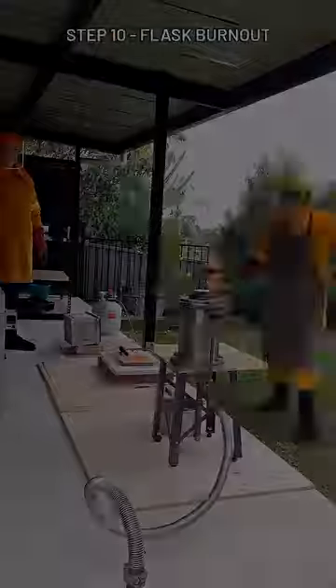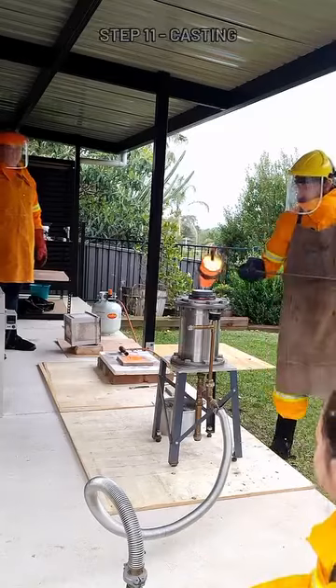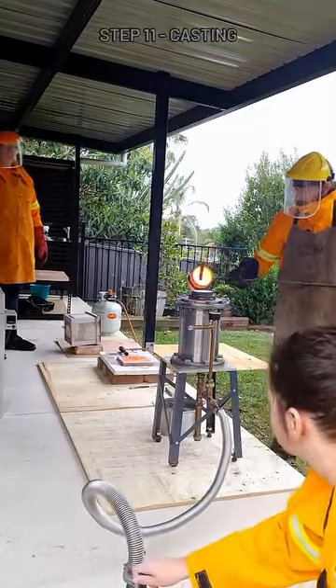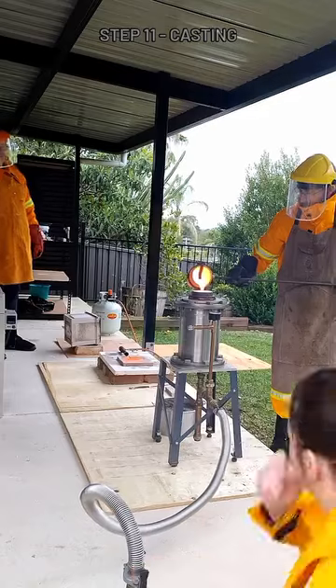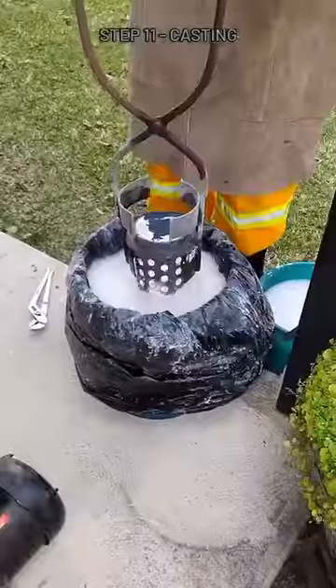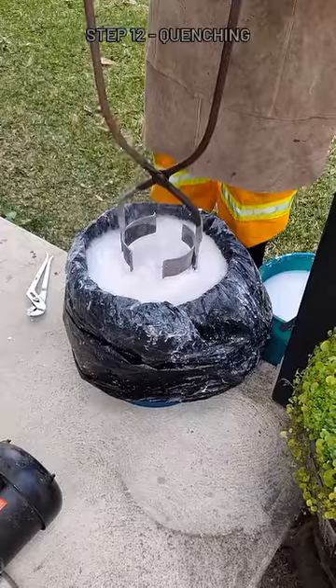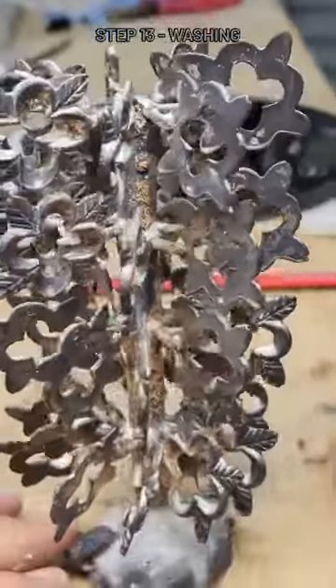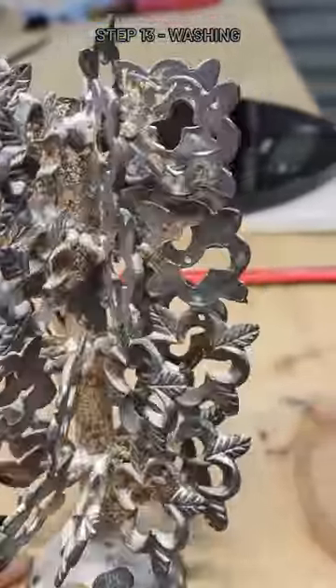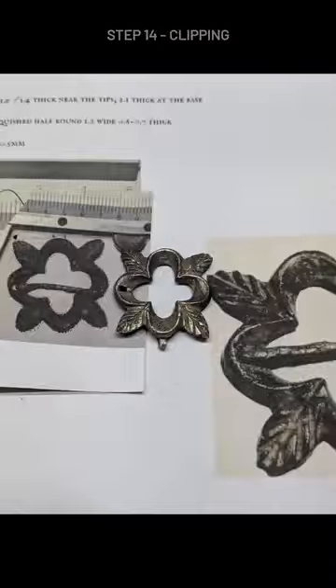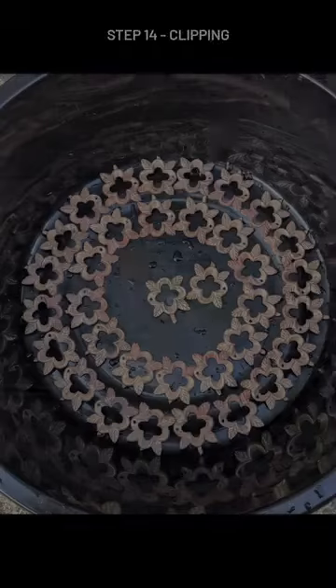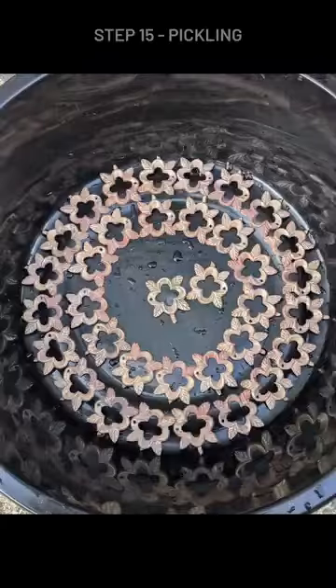15 or so hours later, the moulds are ready to accept the molten bronze at 1000 degrees. A quick dunk in the quenching bucket, and the wax tree is now revealed to be a bronze tree. The brooches then get clipped from the main tree, and they spend 24 hours in a pickling acid to remove any oxide or residual plaster.